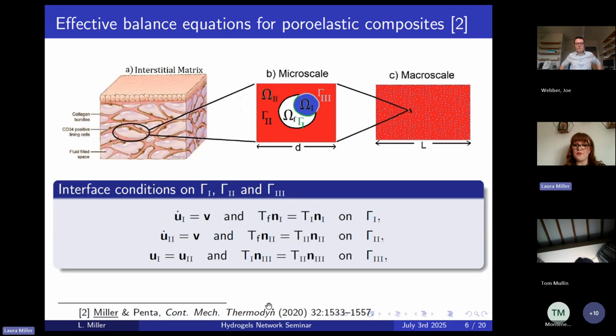Then I require some interface conditions to close the problem. In this case, I'm going to have three different interfaces that I can describe. The interface gamma 1, which, if you can see it, is in green here, is between my fibre and the fluid-filled pore. On that gamma 1, I have the continuity of the velocity with the time derivative of our solid displacement, or just our solid velocity. I also have the continuity of stress, that is, the continuity of the fluid stress with the solid stress in that compartment, on gamma 1.